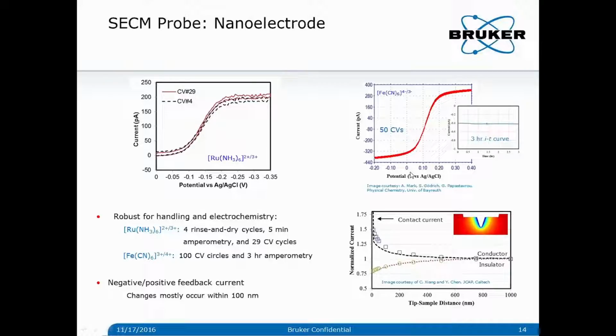Of course, we get a CV curve and a tip current, but how do we know the tip current is from the very tip apex instead of somewhere leaking? Then we go ahead to capture the approach curve, which can also tell you the spatial sensitivity of the electrochemistry. This curve displays the relationship between the tip current and the tip-sample distance. The dotted line is the experimental result, and the symbol line is the COMSOL simulation. As you can see, our experimental results are very consistent with the COMSOL simulation.